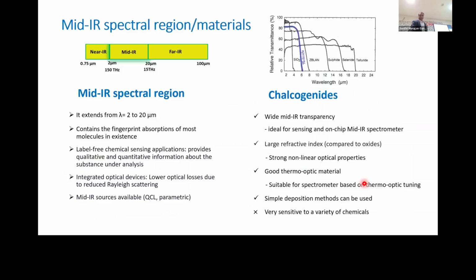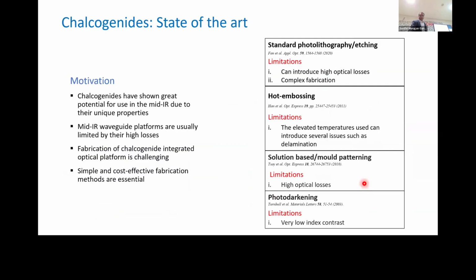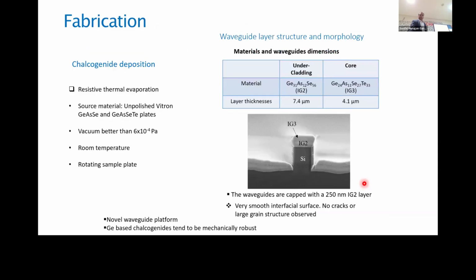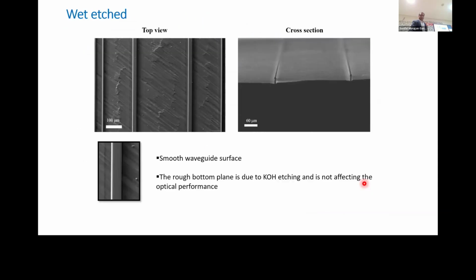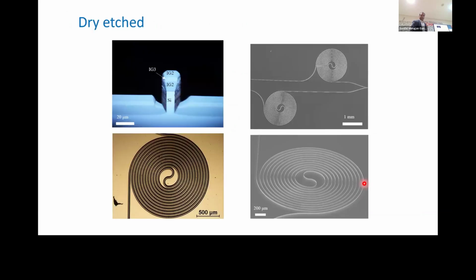Similarly, chalcogenide waveguides: if some of you are interested in chalcogenides, you know that they are very delicate materials to deal with. Therefore, we found a good way of fabricating waveguides which are like this. So you have pre-patterned silicon, then we deposit chalcogenide layers. For example, Ig2, which is one of the chalcogenides, is germanium arsenic selenide, and Ig3 is germanium arsenic selenium and telluride, and Ig3 has a higher refractive index.